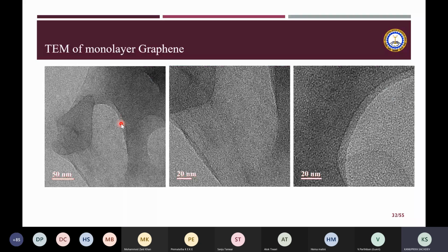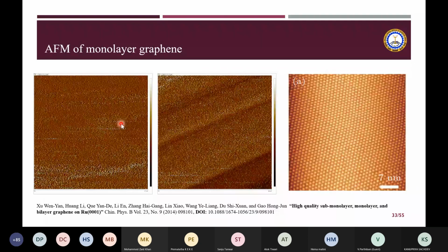This is the micrograph. Although this is not very clear, this is a high resolution picture. If you look at the atomic force microscope image of this monolayer graphene, this is a really beautiful picture, where you can see the hexagonal arrangement of carbon atoms. This was a high quality sub-monolayer, monolayer and bilayer graphene on Ru(0001) grown by these authors, in a paper published in 2014. And this is a very beautiful picture of a single layer graphene seen by the atomic force microscope.